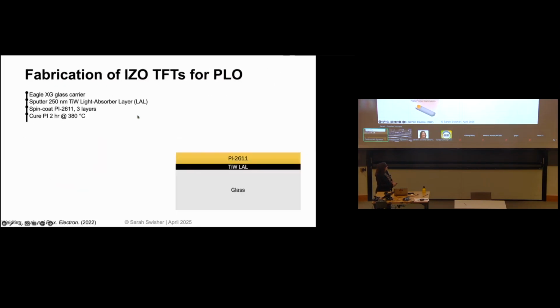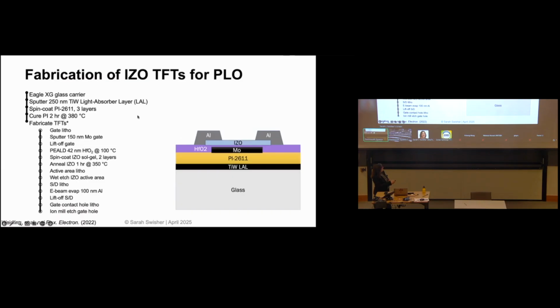Okay? So to do this, first we fabricate the glass. We use titanium tungsten as the light absorber layer. We use a polyimide spin-on as the plastic. So this is our substrate now, our lift-off substrate. And then we do whatever device fabrication you want to do. In our case, we're going to make this indium zinc oxide transistor again. Okay? So for these devices, we actually thermally annealed this indium zinc oxide, and we're working on using the photonic curing for this part as well. The performance of these devices is going to be a little bit lower because we thermally annealed these at about 350. So we expect the device performance to be lower. But what we see is that during this whole step, right, multiple layers of evaporation, lithography, deposition, etching, all of that, the device is supported by the glass substrate.